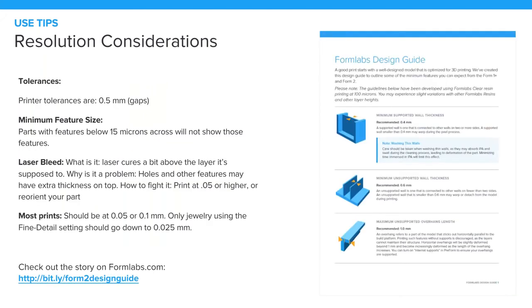If you're interested in learning more about this stuff, we have a bunch of design guides online. 50 microns we recommend because it will also give you faster and more reliable prints. 25 microns is more susceptible to laser bleed over time on a large part. On small parts, it's fine, but on larger parts, the laser might penetrate through the resin a little bit extra. So if you have a circle, it might be slightly flattened on the side of the circle that faces the bottom of the tank. Again, if you want more detail about this, you can go online.